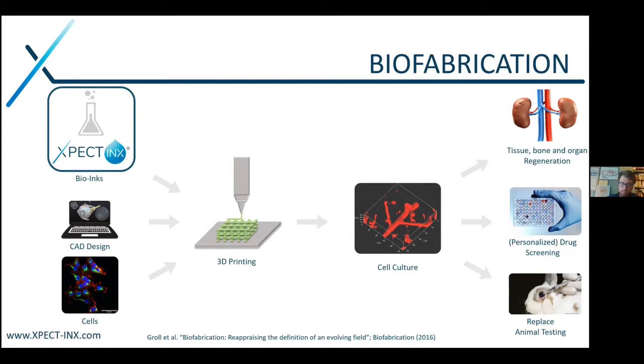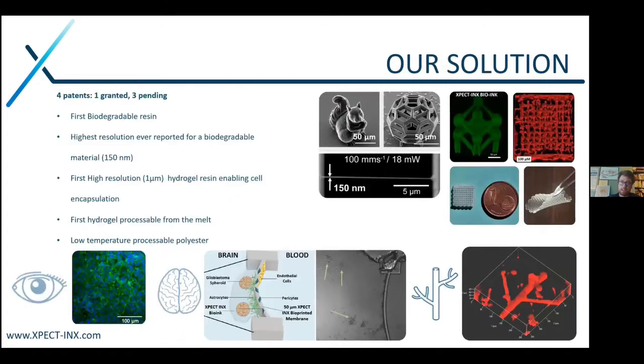And then we were looking at which assets we already have. So we have 4 patents, of which 1 is granted and 3 are pending, which resulted in some materials with quite some unique features. For example, we were one of the first to have a biodegradable high-resolution resin and managed to process it at the highest resolution ever reported for a biodegradable material, so down to 150 nanometers.